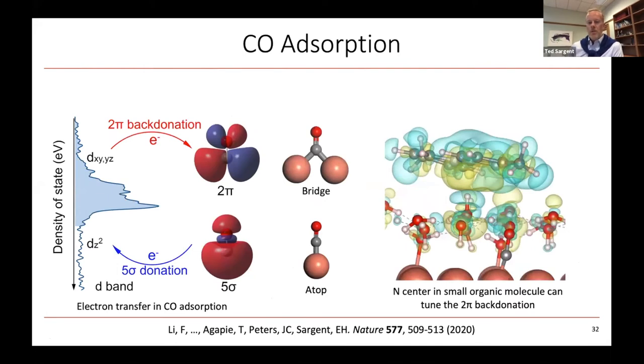And so diving in a little bit further on that, we sort of asked the question, could we think of molecular strategies that could be helpful? And here we started to reason that the bridge corresponds to an electron back donation from the catalyst related to the 2 pi orbital. And that the atop corresponds to the sigma donation scheme, where the bonding orbital of the CO donates to the surface. And that if we could find ways to manipulate the ratio of these two configurations, we would have something.